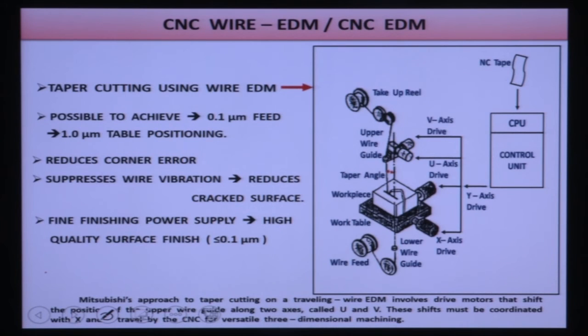So any kind of 3D surface can be made into the workpiece. This is the CNC wire EDM system. You can see here the V axis and U axis. Taper cutting can be done using this CNC wire EDM. It is possible to achieve 0.1 micron feed and 1 micron table positioning, and it reduces the corner error, suppresses wire vibration and reduces the cracked surface. With a fine finishing power supply, the surface quality is less than 0.1 micron.